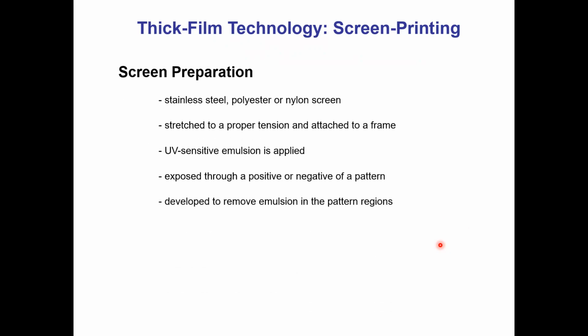So what is thick film technology? It's known as screen printing as well. There is a screen, which is made of stainless steel or polyester or nylon screen attached with proper tension to a stainless steel frame. Then if you want to print particularly a patterned device, you can cover the entire screen with UV sensitive photo emulsion, and then you can use a mask through which you can shine UV light to replicate that pattern on the screen, and then you can use that patterned screen